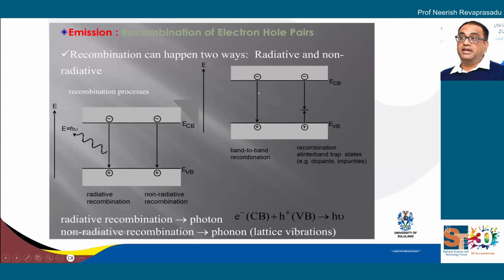Now, here you have band-to-band recombination, or you can have recombination via trap states. So the electron can go up and it can come down and it can get trapped. And what traps the electron are defects. For chemists, what is important is that these defects are related to the surface of the quantum dot. And the surface of the quantum dot has to be passivated by organic ligands or capping groups, and that prevents any defect emission. So what we really want is clean emission, or band-to-band recombination, giving you a good quality photon of light.